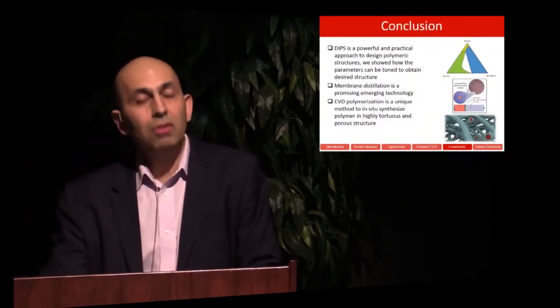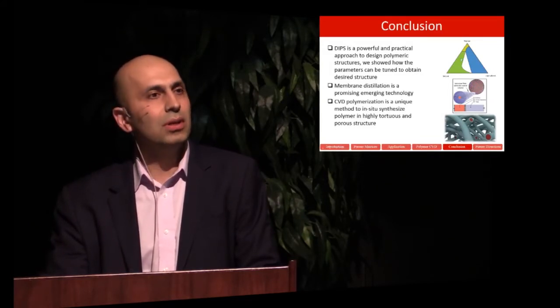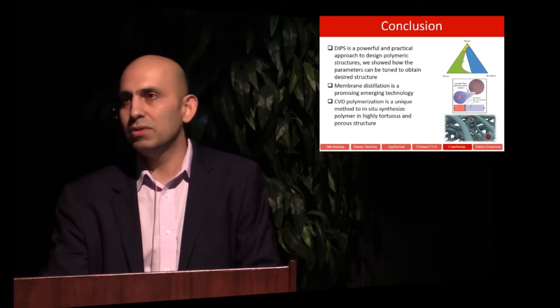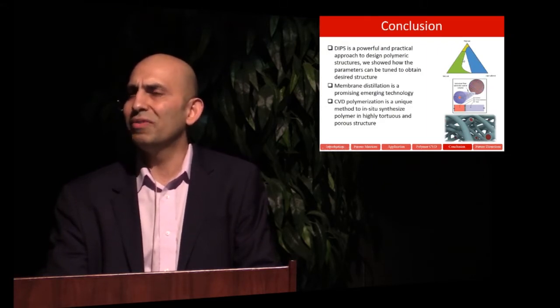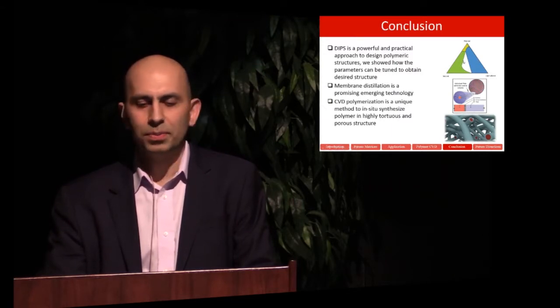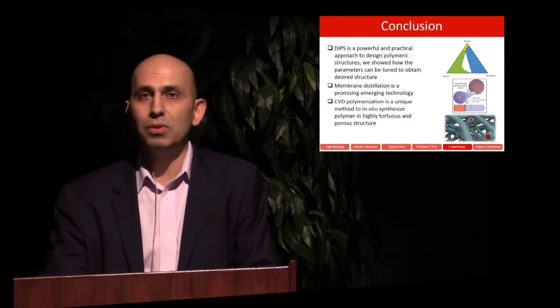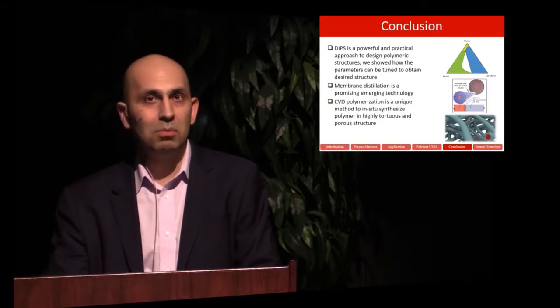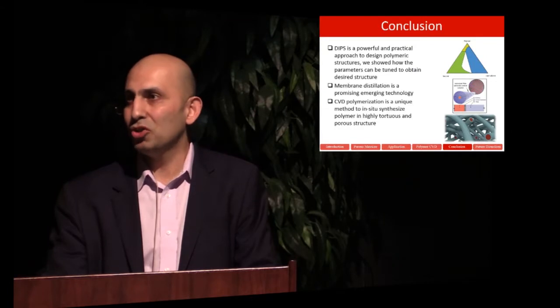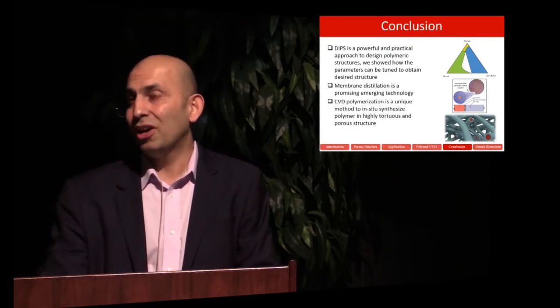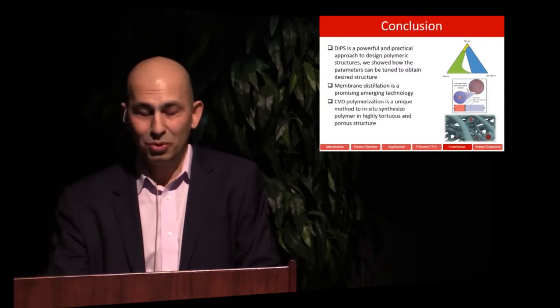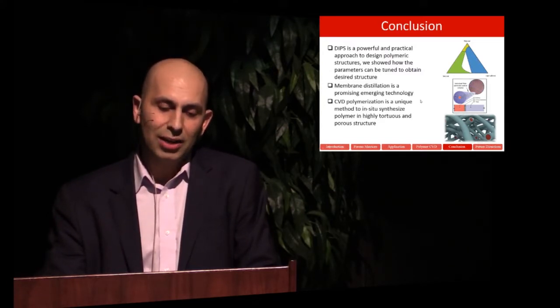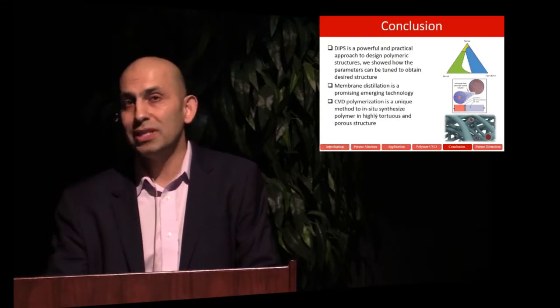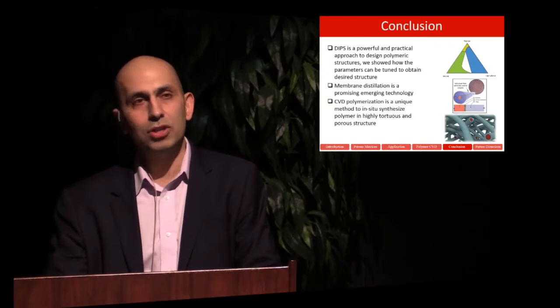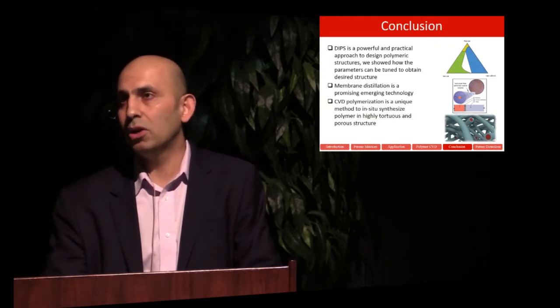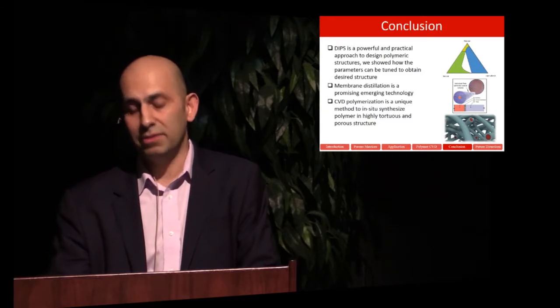So in conclusion, I would like to again point out the DIPS, which is the diffusion-induced phase separation method, as a very robust method to make polymeric structure. I also showed you how easily we can close the technology gap in the MD and make much more attractive membranes and address the challenges in the MD world. And lastly, I showed you the CVD polymerization, which is a new technique for adjusting the surface wettability and chemical identity of materials at the surface.